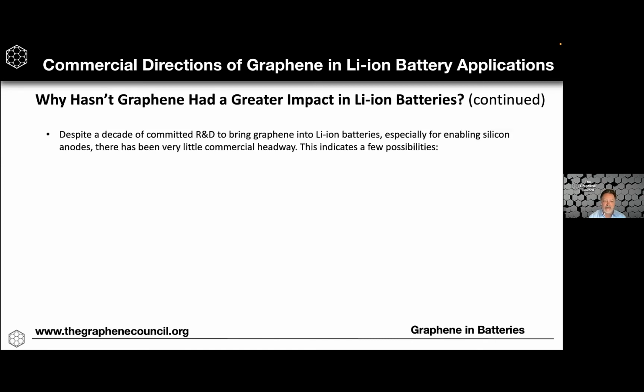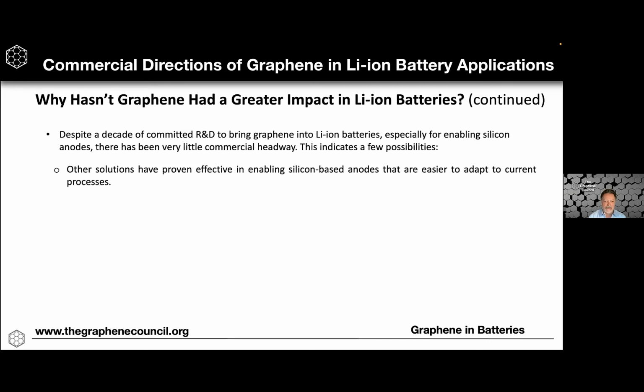Continue on this. So the issue with silicon anodes, and this is where most of the commercial interest has been in using graphene for lithium-ion batteries. One issue could be that other solutions are proving fairly effective in enabling silicon-based anodes. These can be pre-lithiation methods, such as controlling the thickness of the lithium through evaporation, which is fairly simple to do and doesn't require use of another material.